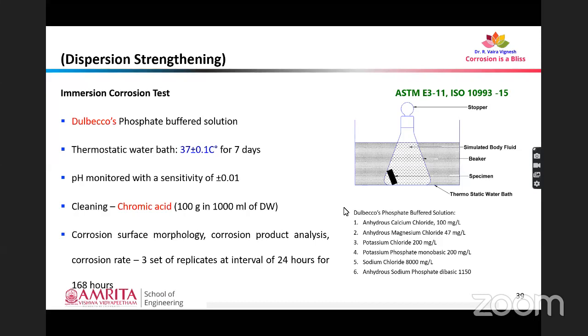And coming towards corrosion analysis, first we have done a basic immersion corrosion test. In this basic immersion test, we have taken the surface composite specimen and immersed it in simulated body fluid. There are many types of simulated body fluids available in the open market. First is Hank's solution, which is what people generally use, and we have used Dulbecco's phosphate buffered solution, and that is advantageous.